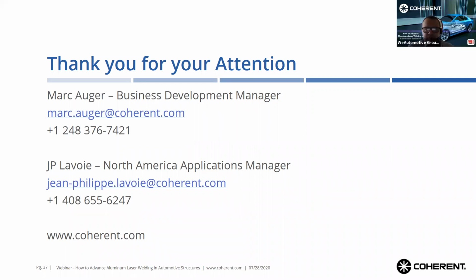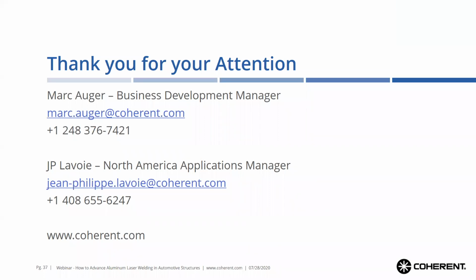Next question. What are the main benefits of ARM laser fibers over standard fiber lasers? Yeah, I can answer that one. It's a great question. We covered a little bit of that, maybe a little quickly at the beginning, but essentially, it really is a different type of laser system. It does wear the name of fiber laser, but having the ring and core and being able to control independently the ring and the core gives you a new knob to turn in the lab when welding challenging materials. And what we see is that in a lot of these challenging materials, in this case aluminum, the ring really helps by being able to preheat and post-heat the material and control in a lot of ways the heat, the cooling rate essentially, of your material.